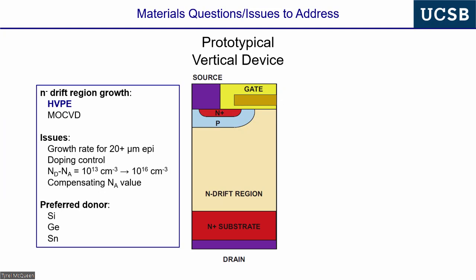And so the other thing at these high growth rates, okay, there's huge concern about having controllable donor doping, okay, with net donor concentrations in the part per billion to part per million range, and having exceptionally low compensating acceptors, okay? And then a lot of work that we've been involved with is actually deciding on the preferred donor. So you notice this goes straight down. There's carbon, silicon, germanium, tin. This is column 4 on the right-hand side of the periodic table.